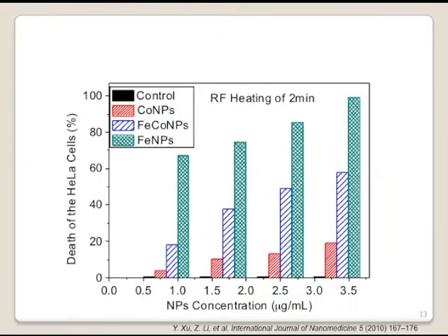Now, if we keep the RF heating time constant, let's say at 2 minutes, we found that the death rate of HeLa cells increased with the concentration of nanoparticles in the media. Especially the iron nanoparticle has a high killing efficiency. With almost 3.5 microgram per milliliter, the iron nanoparticle can kill almost 100% of the HeLa cells.